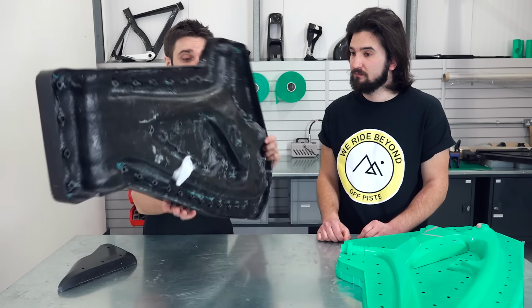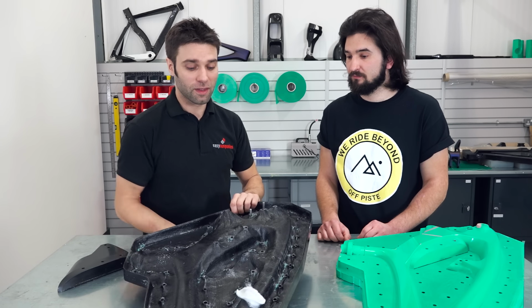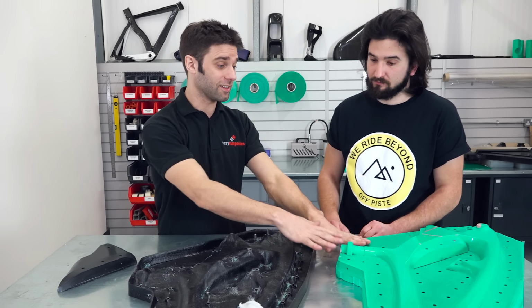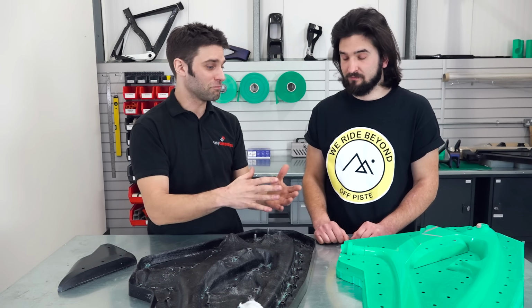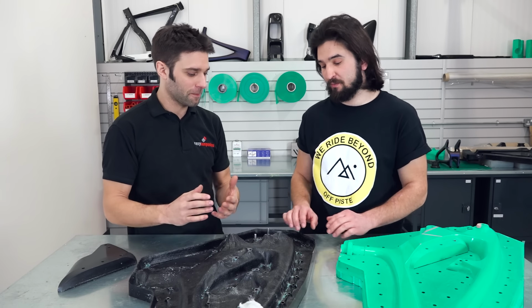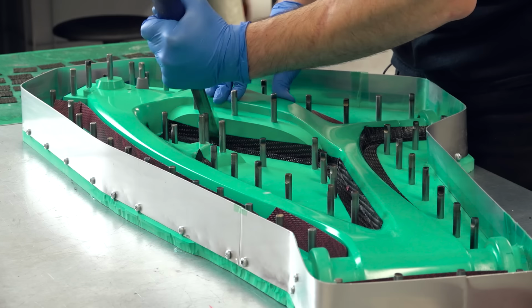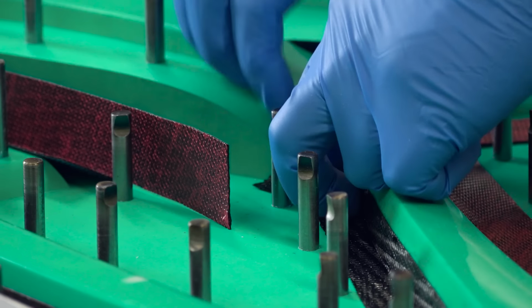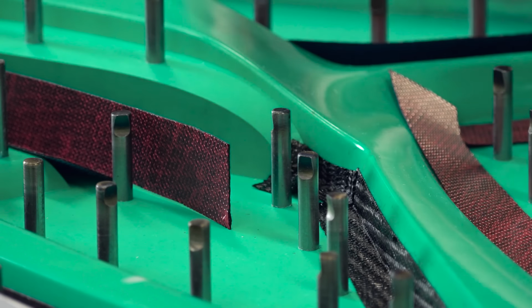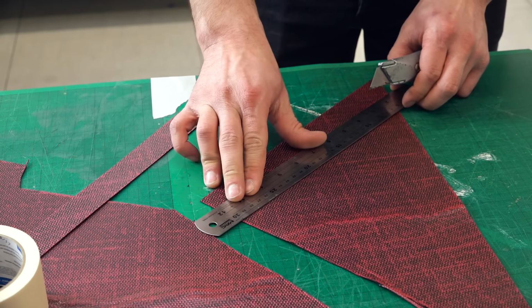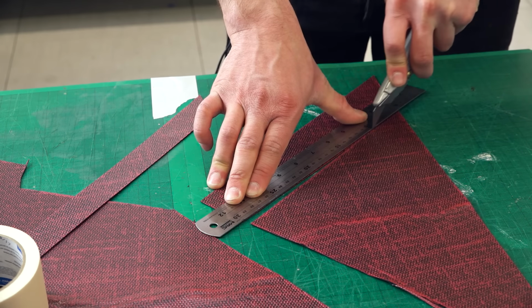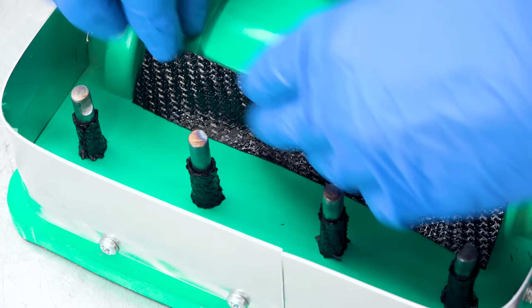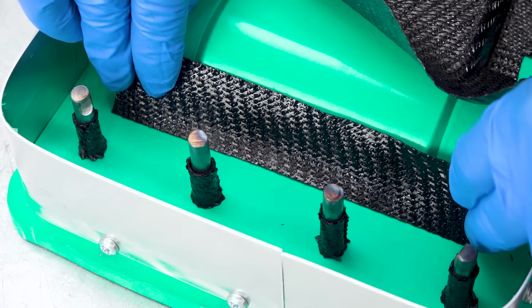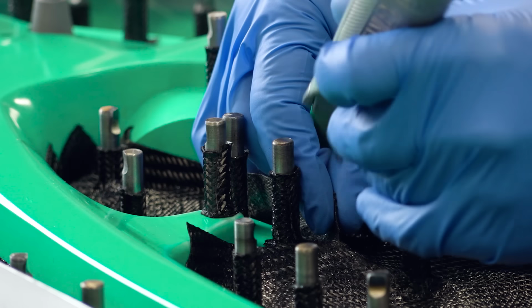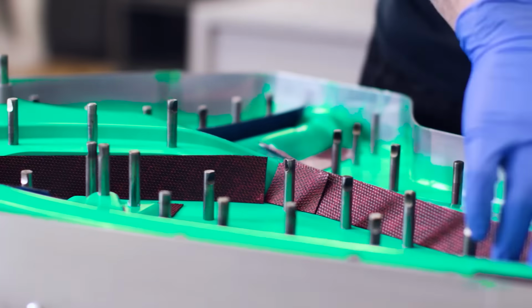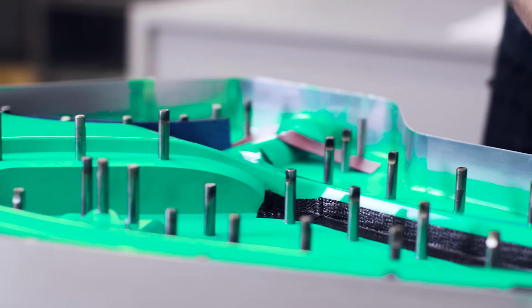Okay, I'm looking at this. It's obviously quite a complex shape that we're looking to form, and this pattern, obviously, that's not going to be laid up in just one piece of material, is it? No, it can't be in one piece of material. I started with the corners, and all corners they go in plus minus 45. So you actually cut the material, the surface ply, thin strips at 45 degrees. Yeah, at 45 degrees. So this ensures that all the corners are pushed in. Same goes for every single pin. So we have little strips of 45 around every single pin. Every single pin. Yeah. That must have taken quite some time to laminate.